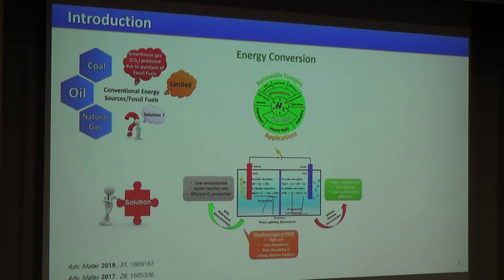And this hydrogen can be manufactured by a number of systems. Among these, nearly 85% of hydrogen is produced through steam reforming, but that is associated with carbon dioxide emission, which is detrimental to the environment. So water electrolysis is another alternative way to produce ultra pure hydrogen, and this water electrolysis system includes two half-cell reactions, that is the cathodic hydrogen evolution reaction and the anodic oxygen evolution reaction.